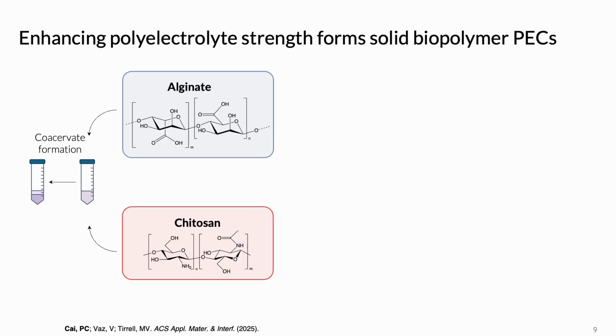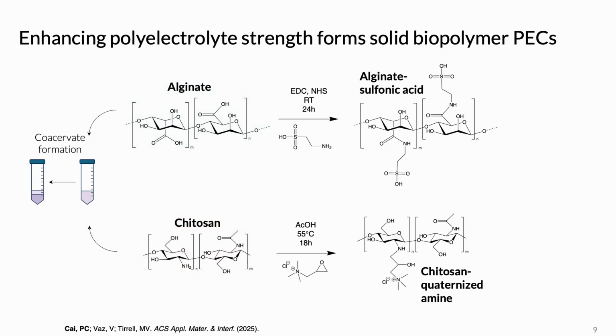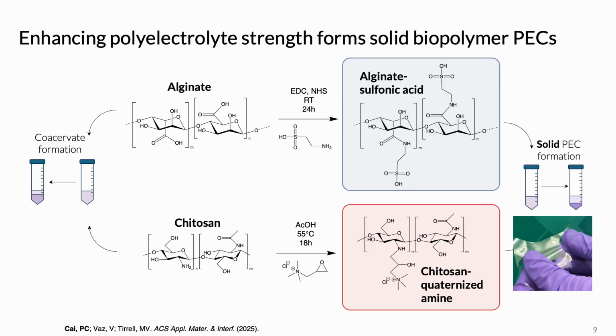But the solid-liquid phase separation never occurred, instead giving me liquid-liquid phase separation. And I tried drying off residual liquid, but the remaining material was very flimsy and had the consistency of tissue paper. So this one was not strong enough to replace plastic. So I made some modifications, and here I'm hypothesizing that by changing the charged groups on alginate and chitosan, I can get that solid-liquid phase separation. And it did happen, and also the resulting solid part gave me this strong, transparent film.